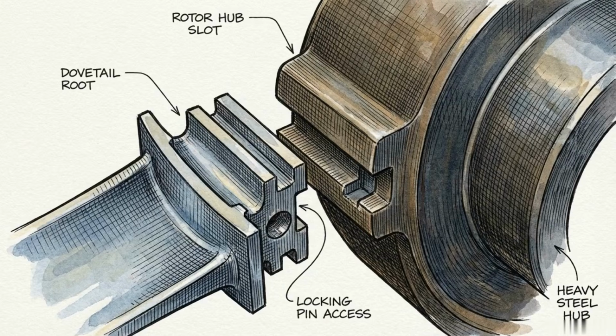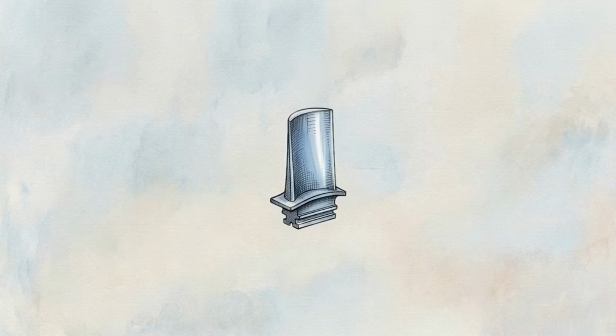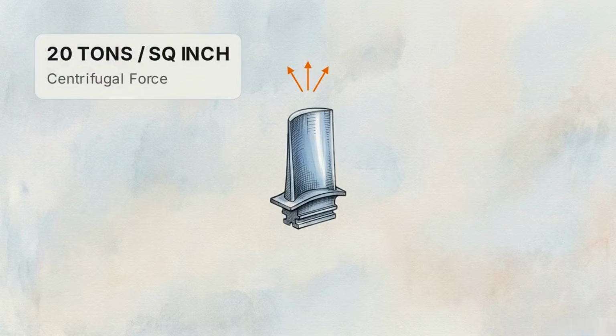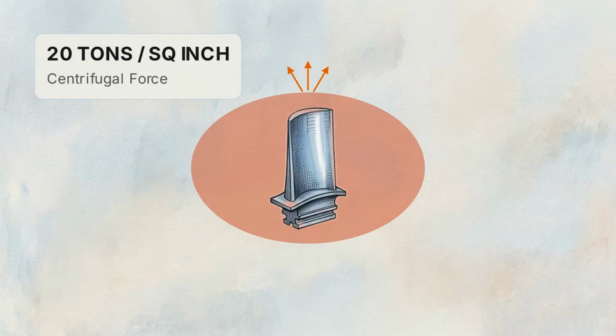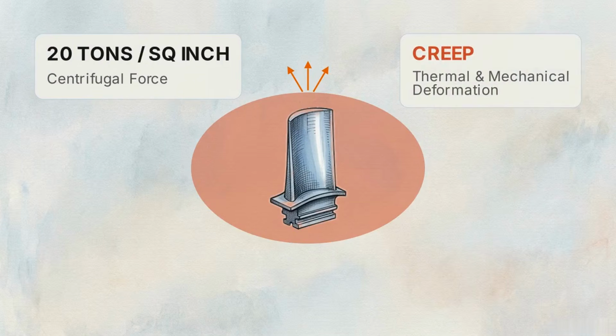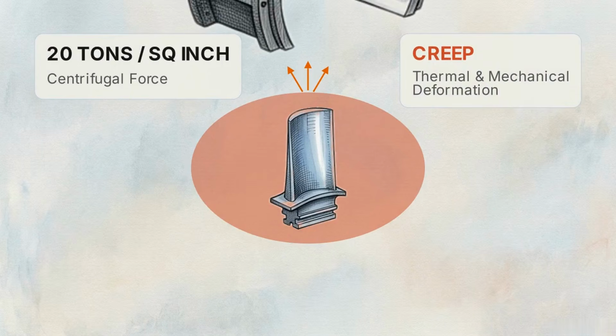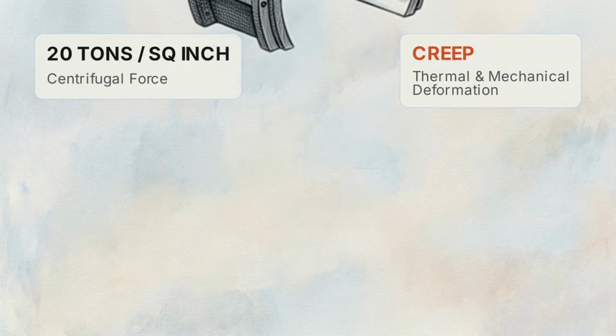The blades positioned directly after the combustor rotate at around 12,000 revolutions per minute. That rotation generates an outward centrifugal pull of about 20 tons per square inch. Expose normal metal to extreme heat and rotational stress, and it stretches over time. Engineers call this creep. Eventually, the metal elongates, scrapes the outer casing, and fractures.